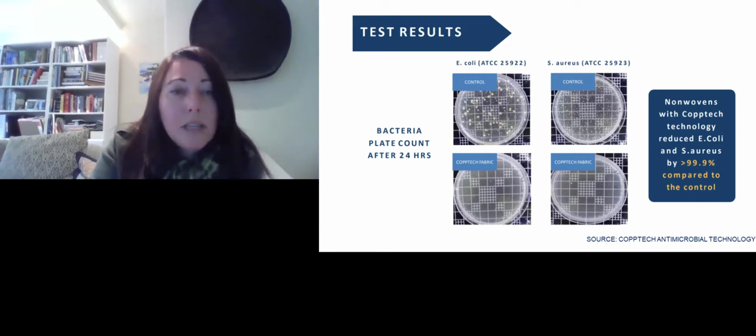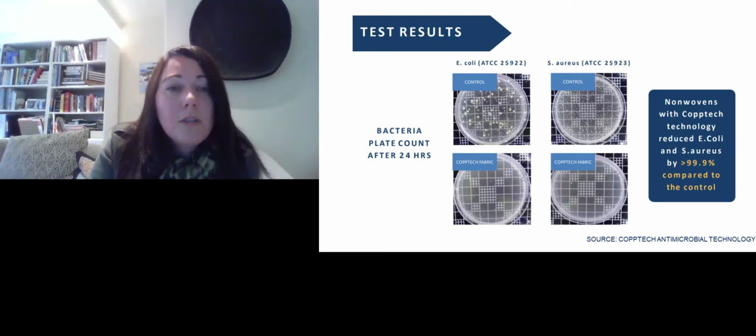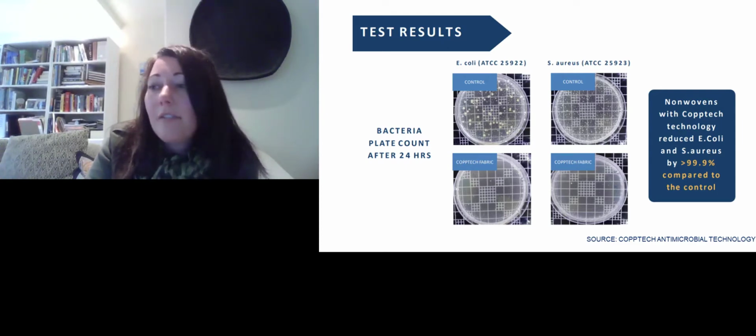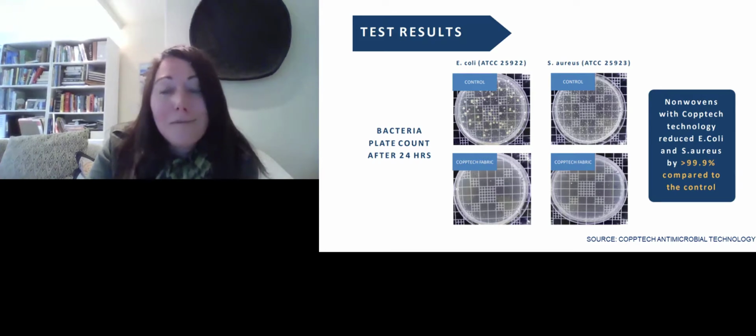I didn't do this test, but if I were to, I would go to my third-party testing and say, I need you to do an AATCC 100, and I need you to test for E. coli and Staphylococcus aureus, which is what you hear about when people get a staph infection. This is staph. And these numbers here are the specific numbers from the testing standard that apply to that bacteria.